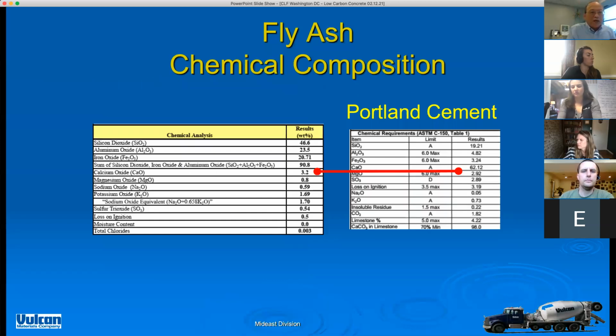Again, looking at the calcium oxide content, you can see that this fly ash, or Class F fly ash, is very, very low in calcium oxide. 3% is what we're looking at, again comparing with 62% from Portland cement. So that's not very reactive at all. As a matter of fact, when you mix fly ash with water, it's going to stay unhydrated forever and ever.